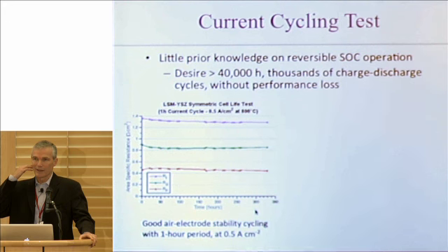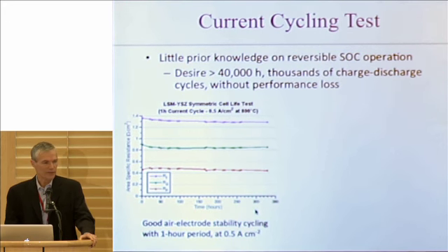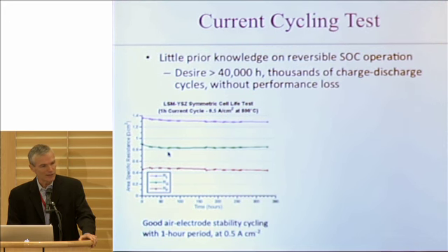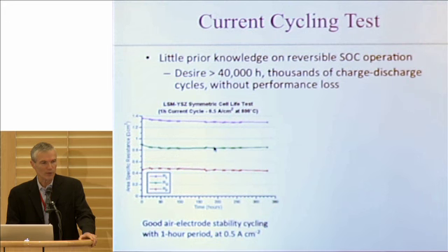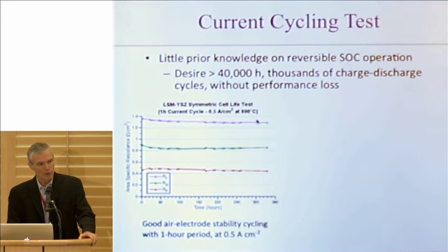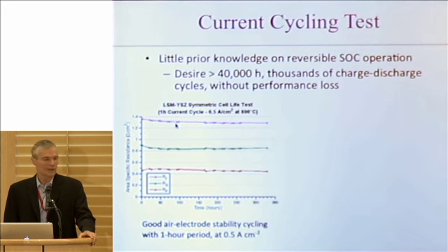Of course, we want to get up much more, like 4,000 or 5,000 cycles, but this is just the beginning. But the good news here, without getting into the details: the red and the green here are just showing different parts of the device. The blue is the overall resistance. You can see the device is actually pretty stable. It's actually improving slightly over these first few hundred hours of operation.